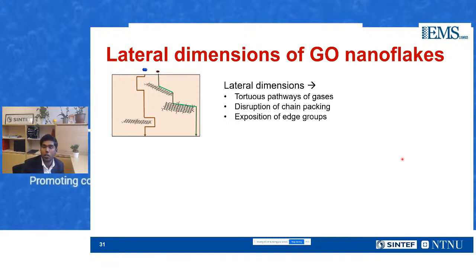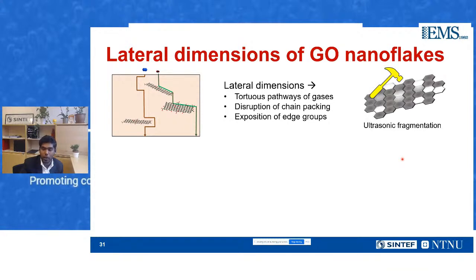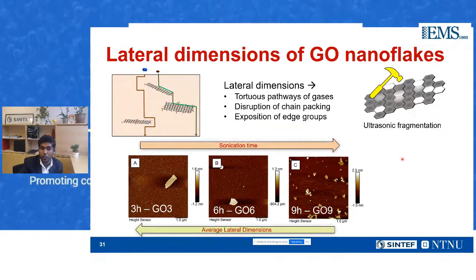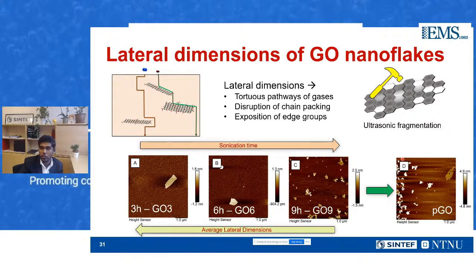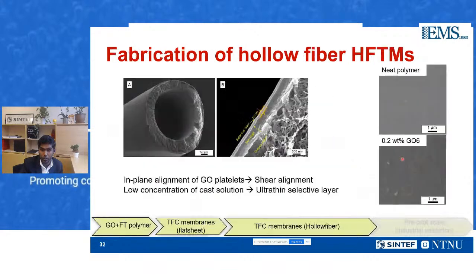So we chose different lateral dimensions of graphene oxide to see if they can change the effect of the graphene oxide dispersion in the polymeric membrane to get better CO2 permeance and selectivity. We used a very normal method, ultrasonic fragmentation. With that fragmentation time, we were able to control the size of the graphene oxide flakes that were dispersed. Basically, when you increase the sonication time, you get reduced lateral dimensions of the graphene oxide. We also made them porous, using the same procedure we described before, so with these 3 dimensions we got 3 different porous graphene oxides of different lateral dimensions.